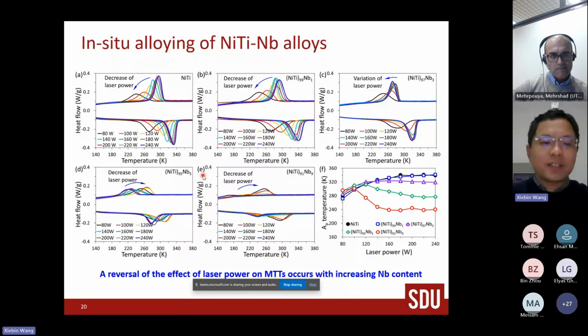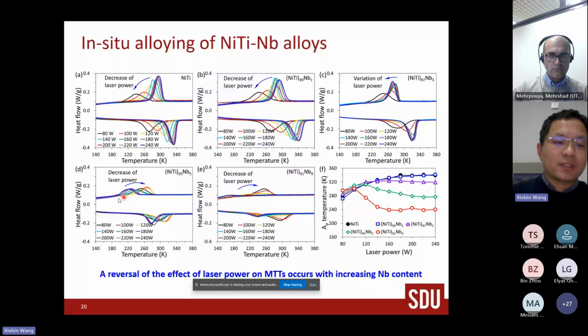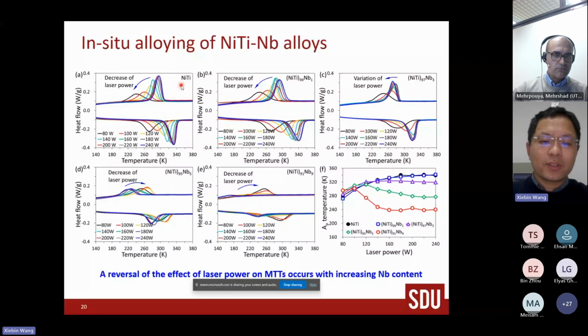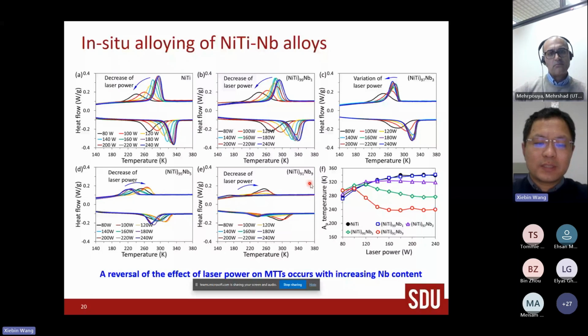And then if you increase the niobium addition to 5%, the transformation temperature actually increases with a decrease of the laser power, or with a decrease of the energy input. It's totally opposite to what is observed in nickel-titanium or 1% niobium alloys. Of course, for the non-niobium samples, it shows a similar trend: decrease of laser power, increase of transformation temperature.